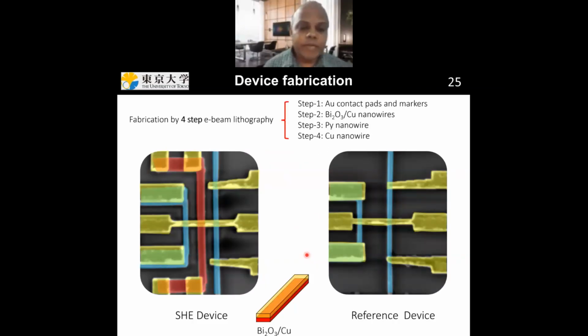To do that, I made two kinds of devices. This is one simple non-local spin valve device, and the other is a device in which I put a bismuth oxide copper bilayer in the middle. This device was made in 4 different steps of electron beam lithography, and it was fabricated by me.